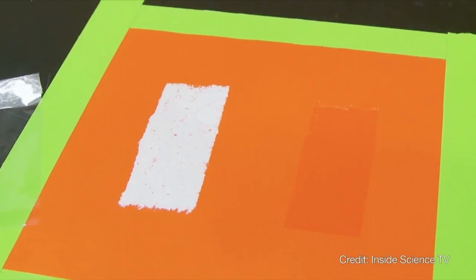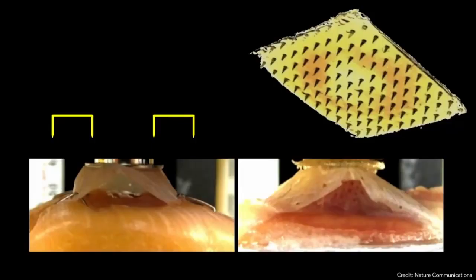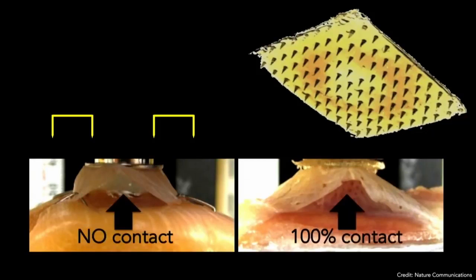You can also start from the solution first. We noticed that spiny-headed worms latch onto their hosts by blowing up their proboscis following insertion. Where might that apply? Swellable microneedles for better skin grafts. So typically, staples are put at the periphery of the graft, and the middle part doesn't always adhere. So we engineered microneedles whose tips swell following insertion into tissue. So this could maximize adhesion and maximize surface area of contact to prevent a painful regrafting procedure.